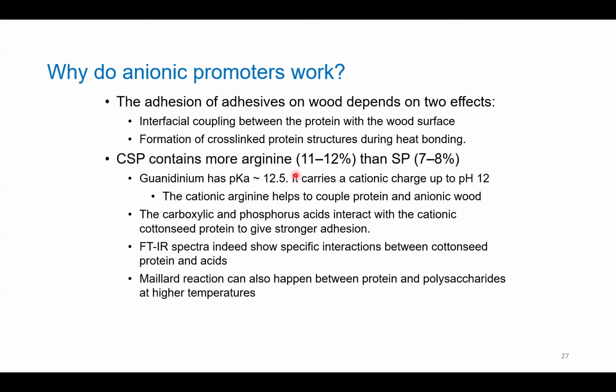Now, cottonseed protein contains a lot more arginine than soy protein. And arginine contains a guanidinium ion, a cation, with a pKa of 12.5, which means it's cationic up to pH 12. And the cationic arginine helps to couple the protein to the wood. The wood in most cases is anionic. Most natural materials tend to oxidize, so the surface tends to be anionic because of oxidation. So having cations helps with binding the anionic wood.